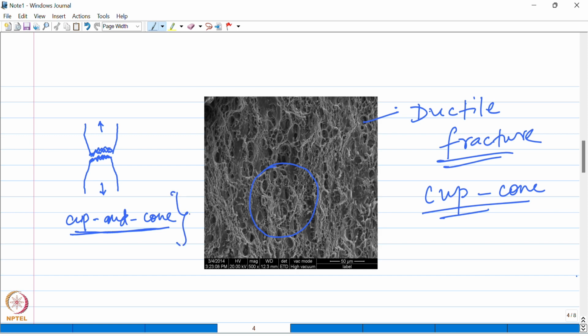So when you have a macroscopic observation of the fractured surface, and if it occurs by the ductile fracture mode, you would see this kind of features looking like a cup and cone pair. And on the microscopic level, when you put it under an electron microscope, you would see these voids, which will indicate that it occurred through the void nucleation and the coalescence process, which is a characteristic feature of ductile fracture.